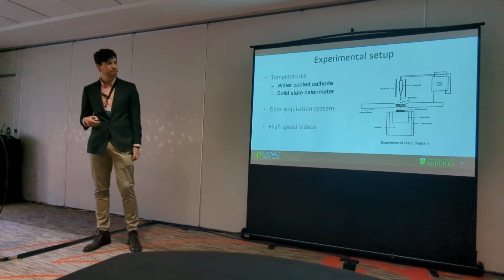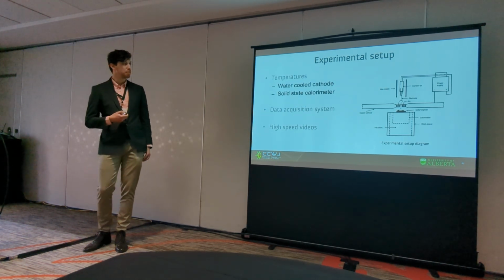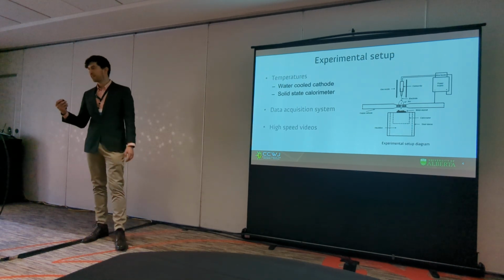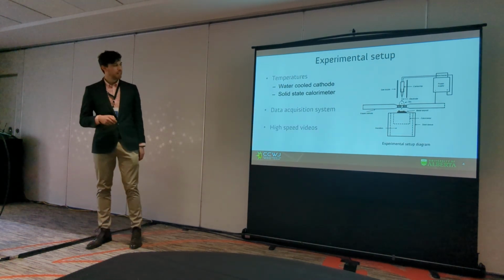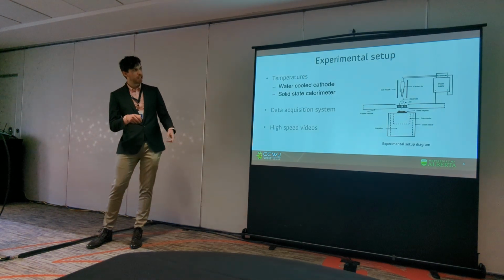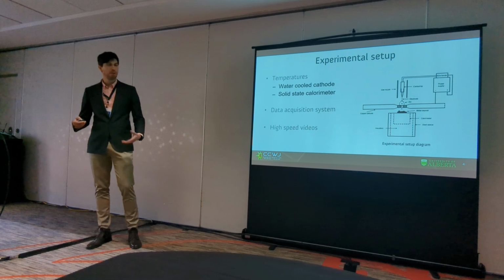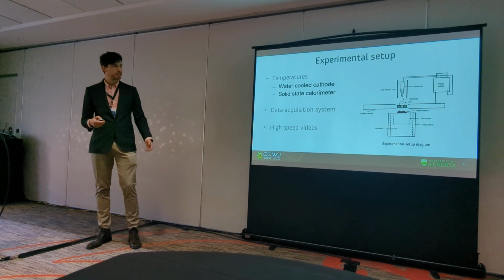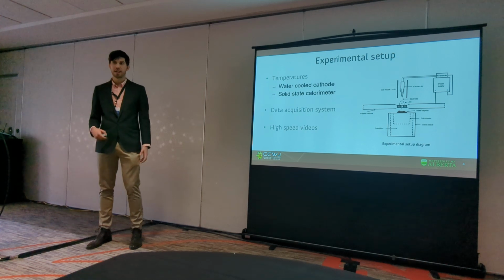that is pure copper. Inside of this calorimeter, we have thermocouples where we can see how the temperature increases while we put these droplets. Also, all this is with a data acquisition system so that we can know the different waveforms from this process. And on top of that, we're going to have high-speed videos to analyze the metal transfer of